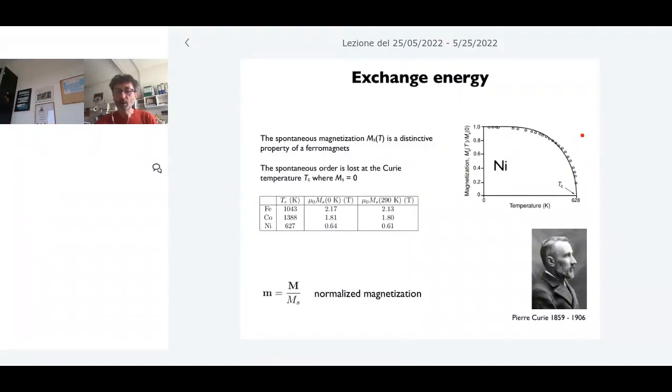So we have always the magnetization as a vector with constant amplitude and changing in direction. This changes a lot the situation, because then we don't need to describe a vector with three independent degrees of freedom. We have only 2 degrees of freedom. That is the direction of the magnetization. It means that in a ferromagnet, the magnetization field is a vector with constant amplitude and variable direction.